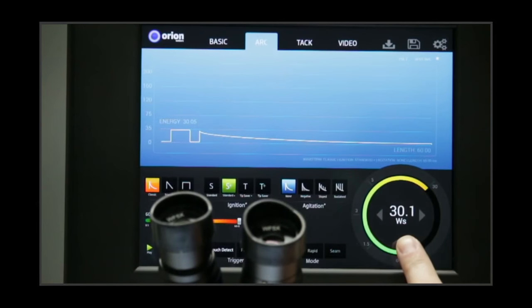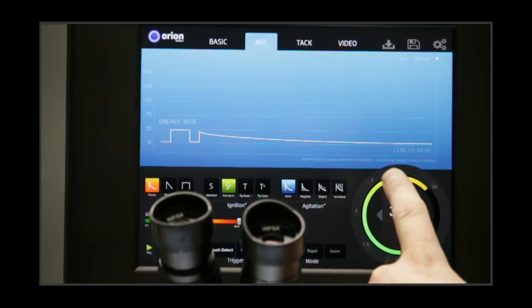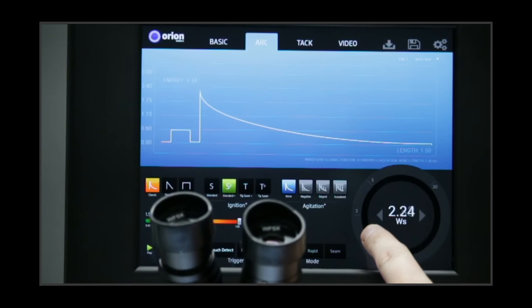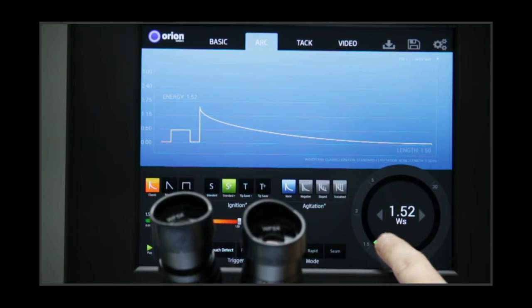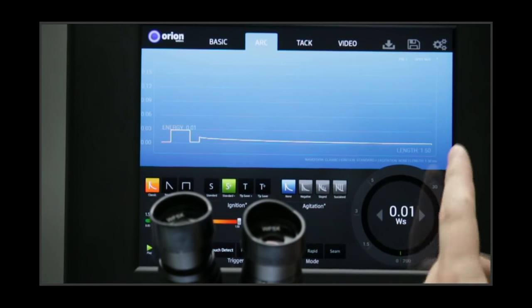So we're going to go ahead and cut back here. And I'm going to go with that chamfer grain here. Right now I've got my welder set, and we can go to that real quick. Right now I've got the welder set at about 30 watt seconds. That's just a ballpark range for this thick of a piece. If I've obviously got a much smaller piece, I'm going to be going down a little bit lower. You can see I can go all the way down on this machine. It goes very, very small.